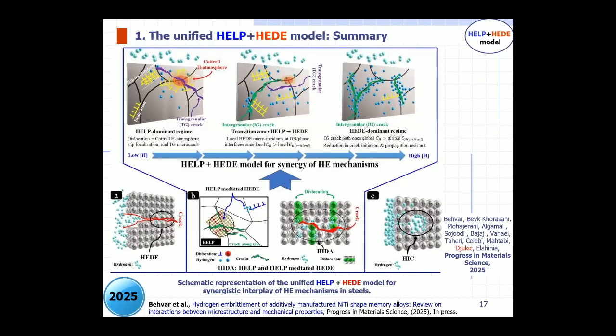Here is the overview in our recent paper in Progress in Materials Science, in press, which is our mutual work on hydrogen embrittlement of one very tricky alloy. It's a nickel titanium shape memory alloy, nitinol. So we provide an overview, including the HELP plus HEDE model. As you can see, we have a HELP-dominated regime, and as a result, ductile failure and some transgranular failure. When we have an increase in hydrogen concentration, we have a transition from HELP to HEDE, and then the appearance of more transgranular or intergranular failure.